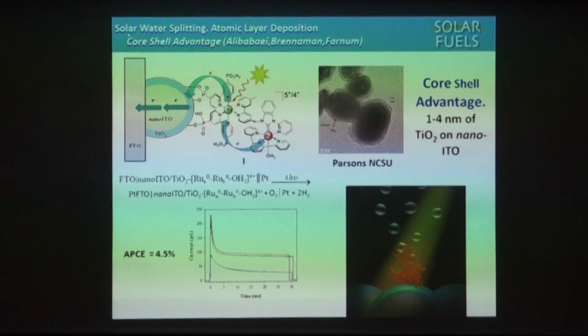And what we did now to do something else was go back to atomic layer deposition. Because what we said is, wait a minute, think about this a different way. You've got this material, nano-ITO, this conducting oxide now in a film format. Go back and use the atomic layer deposition one more time and put a very thin layer of TiO₂. You don't need a thick layer. That's fast, the TiO₂ is slow, so make that very thin. When you do that, and this, by the way, shows a transmission electron micrograph that shows on the outside the shell of TiO₂ on a core of nano-ITO, core shell.